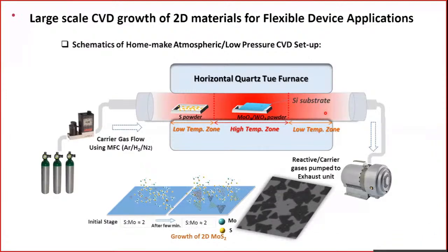Just to give you a brief idea about CVD growth, how do we grow CVD 2D materials, especially on a large scale. Of course, we have MoO3 or WO3. There are multiple possibilities. We can use many metallic precursors. Typically in our group, we use oxide precursors, say MoO3 or WO3. We keep it in a high temperature zone. The growth temperature would be around 850 degrees Celsius. And sulfur undergoes sublimation; its melting point is also very low. So that will be kept in a low temperature zone around 200 degrees Celsius.